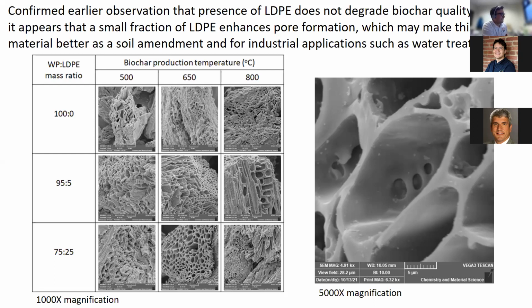Let me just define pyrolysis as it's not burning because we're not adding oxygen. This is thermochemical processing at high temperature, so 500 to 800 degrees C, in the absence of oxygen. So the material doesn't burn, but it does produce a number of co-products, one of which that we're focusing on is biochar, which is carbonaceous material that's very stable and recalcitrant. So the pyrolysis reaction will concentrate the carbon into the solid phase, as opposed to incineration or burning that would convert that carbon into CO2, which would go off in the gas phase. So pyrolysis is distinctly different from burning or incineration.